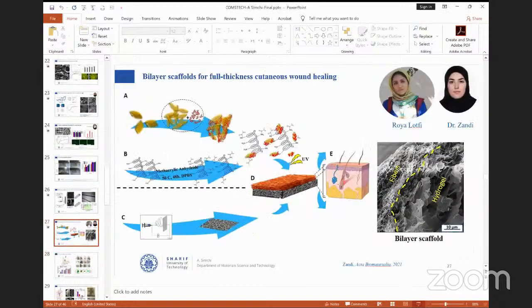In following, we try to make it even more active if the skin is injured from a very deep injury. So it's not only in the epidermal layer, it's in the underlayer as well. Therefore, we had in mind to prepare a two-layer structure. The first layer, as you see in the downside figure, is a fibrous mat, and the upper side contains a hydrogel containing biomolecules and so on. So we made two layers. One layer is fibrous, the top layer is a hydrogel.